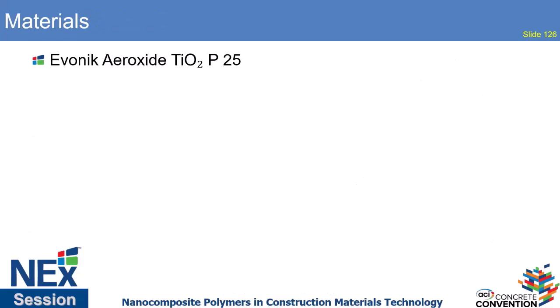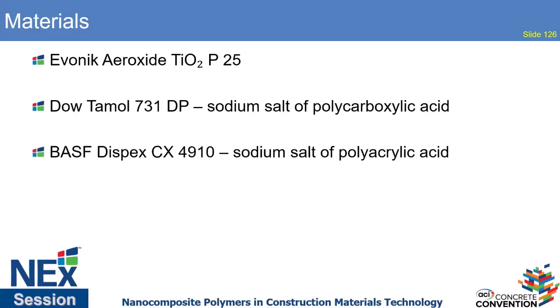In this study, we have chosen to work with the Evonik Aeroxide titanium dioxide P25 particles, which is a 3:1 anatase to rutile crystal grade. It's 35 to 65 square meters per gram surface area. The two surfactants that we have chosen to work with are the Dow Tamol 731 DP and the BASF Dispex CX4910. The first one is a sodium salt of polycarboxylic acid, and the second one is a sodium salt of polyacrylic acid. We have intentionally chosen to work with those two commercially available surfactants. The first one is a commonly used surfactant for dispersion of inorganic pigments, but it's also used in many different coatings. The second surfactant is used more as a dispersant in dried powder materials, so it would be something like grouts and other cementitious materials.